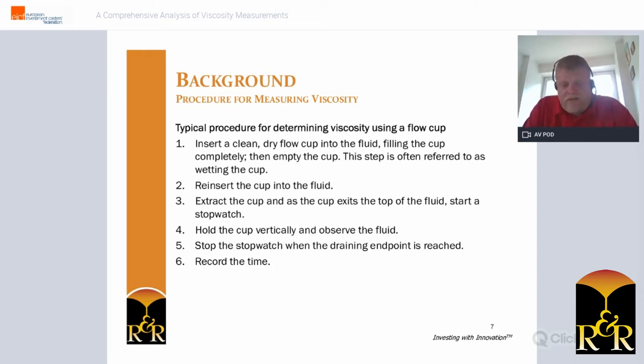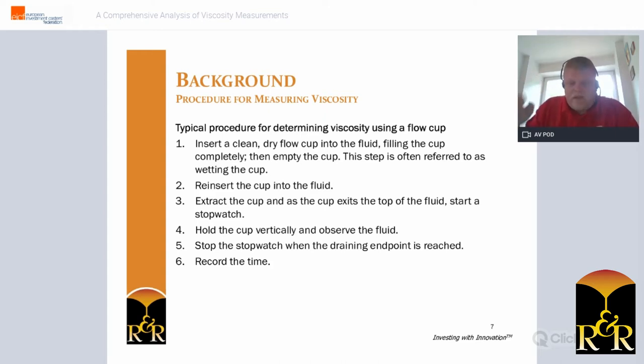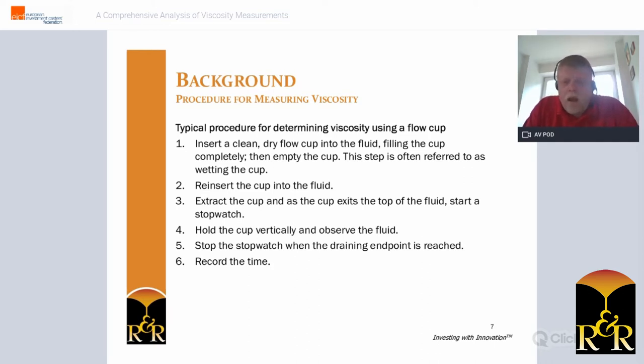After the cup is fully wetted, we reinsert it into the slurry, and as the cup is removed and clears the top of the slurry, a stopwatch is started. Be sure to hold the cup vertically to ensure even flow out of the cup. Once the draining endpoint is reached, stop the stopwatch and record the time.